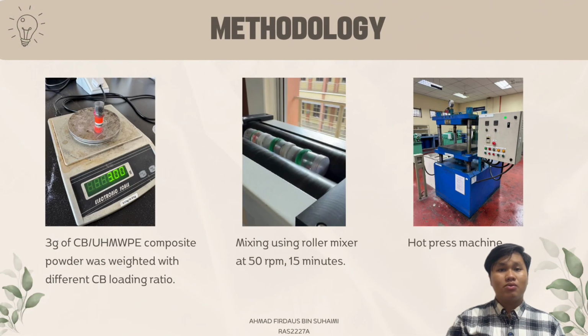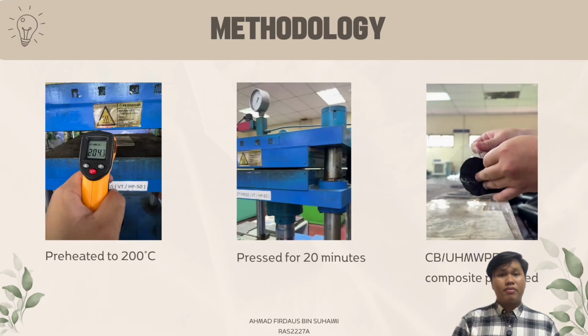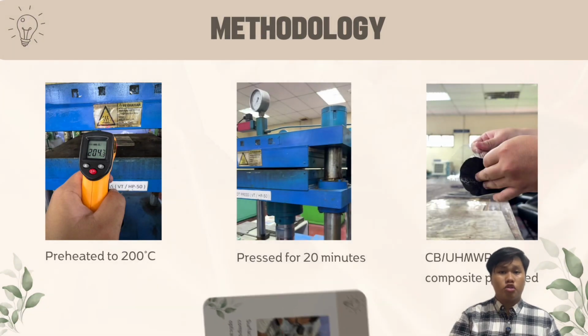Okay, now let's proceed with the methodology. First of all, 3 grams of carbon black with ultra-high molecular weight polyethylene composite powder was weighed with different carbon black loading ratio and then mixed by using roller mixer at 50 rpm for about 15 minutes. And the hot press machine was preheated to 200 degrees Celsius. After that, the powder was pressed for 20 minutes under 5 MPa pressure, and lastly, the composite was produced.